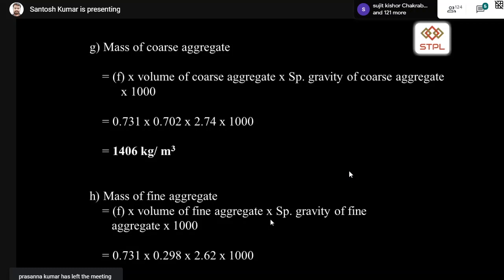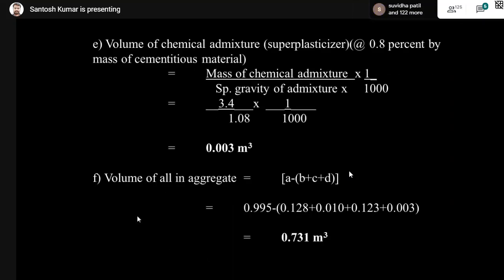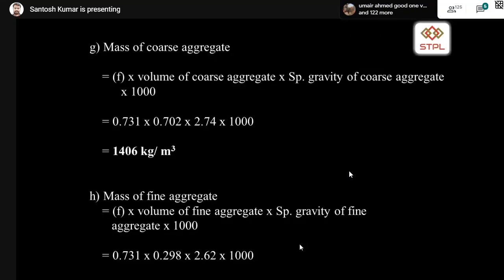So out of that, how to calculate the mass of coarse aggregate? Here you can see the volume of all-in aggregate is F. F is nothing but 0.731 cubic meter. So F multiplied by volume of coarse aggregate, multiplied by specific gravity of coarse aggregate, multiplied by 1000. F is 0.731, the volume of all-in aggregate, multiplied by the volume fraction of coarse aggregate 0.702, multiplied by specific gravity considered at 2.74, multiplied by 1000. So the mass of coarse aggregate is 1406 kg per cubic meter.